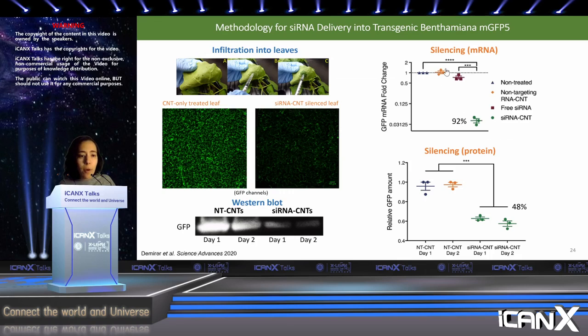We can also perform controls, for example, in the delivery of RNA that does not target GFP, where we don't observe any silencing. If we introduce siRNA that does not target GFP, we see no silencing. If we introduce siRNA that does target GFP without carbon nanotubes, we see some degree of silencing, but much greater silencing if the RNA is delivered with carbon nanotubes. And this is quantified with a qPCR, and this is quantified with a Western blot. So here we're quantifying mRNA, here we're quantifying GFP protein.